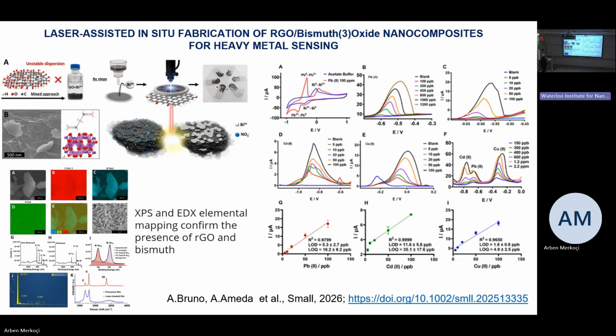Also, we reported recently heavy metal detection. This is still a very, very important area of research because detection of heavy metals overall at low levels of concentration is problematic because of the interferences between the different heavy metals. So we are able to use this technology, the same laser scribing based graphene patterning, using these sensors for heavy metal detection. You see here the response, for example, toward different heavy metals, cadmium, lead, copper, and some responses, calibration curves for the different metals with interest for water monitoring.